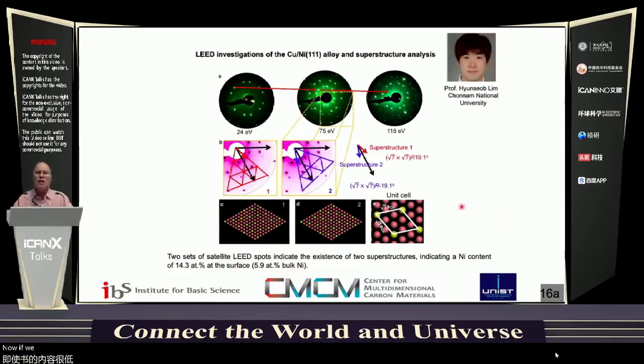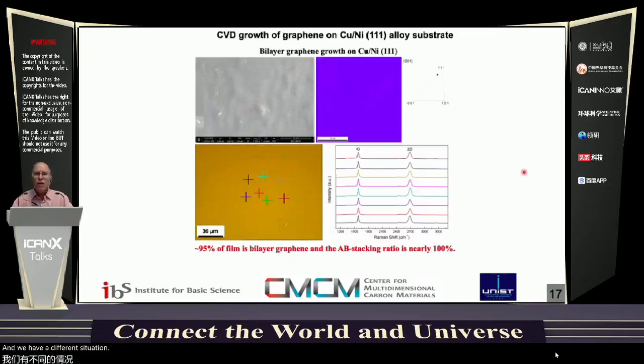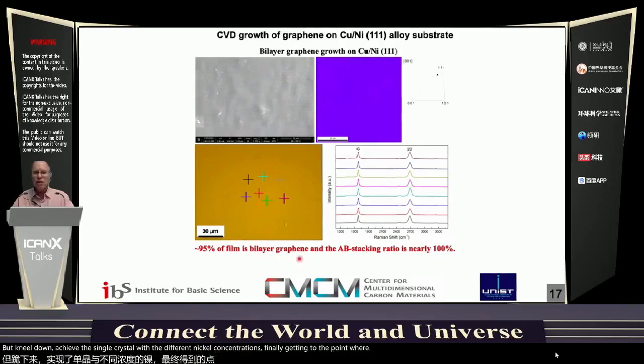Now, if we push the nickel concentration up higher, this disappears and we have a different situation. And this was Ming's hard work in the lab, and a parametric study. So making many, many, many samples to then anneal them, achieve the single crystal with different nickel concentrations, finally getting to the point where over multi-centimeters, 95% of the film could be bilayer graphene, and almost all of that was AB stacked. And this AB stacking is very important in terms of this single layer diamond that I'm going to come to in a moment.